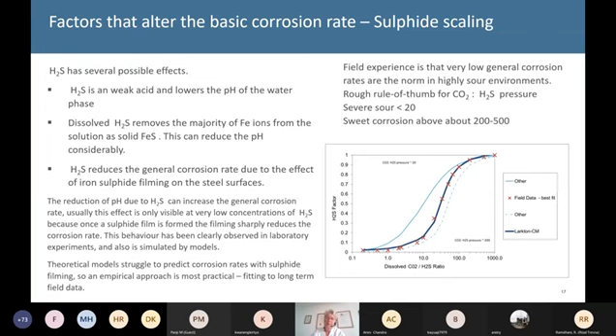What we do know is that from experience, if you're in very sour conditions where you've got a higher amount of H2S to CO2, so you're sort of in this area of this graph, then the hydrogen sulfide does not affect your CO2 corrosion rate very much. I beg your pardon, where you've got a high CO2, which is at the top end of this graph on the right-hand side, you don't have much reduction, so your H2S factor is a high number, so it's not reducing your corrosion value very much. But as you get increasing amounts of H2S, then you get down to the bottom here and you'll get a real drop down of your corrosion rate.